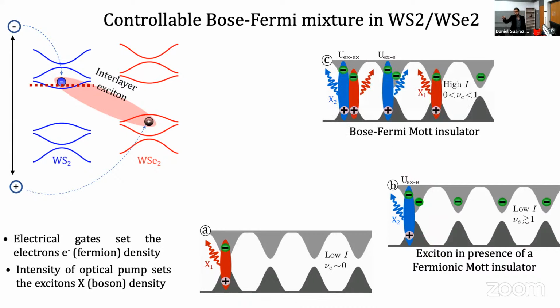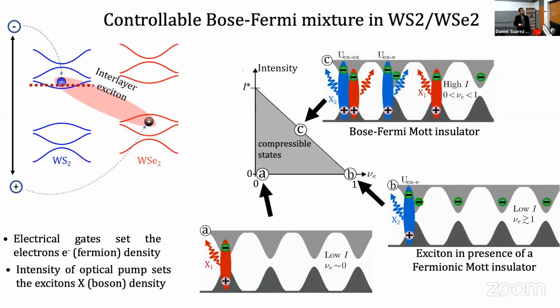And we can then, for example, reduce slightly the number of electrons in the material, but increase the number of bosons by increasing the optical intensity. And we can have a mixture between bosons and fermions in our material. So we can effectively achieve Bose-Fermi Mott insulating states in this material. The comprehensive understanding of these situations gives us a very interesting phase diagram in which we have an edge with incompressible states and then a compressible bulk in the middle.